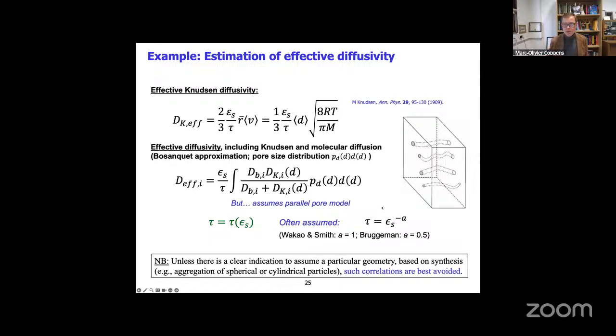And oftentimes a simplified power law relation is used. You find it in Wakao and Smith's work in the 1960s, or Bruggeman's going back even to the 1930s. Even to these dates, this is what's typically used, if not even a constant factor like 3 or 4. But it's often quite arbitrary, these factors, as we'll see. So unless there is a clear indication to assume a particular geometry, it's actually quite dangerous to do that.